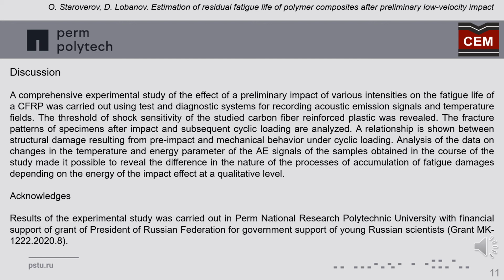The thresholds of the shock sensitivity of the studied carbon fiber reinforced plastics were detected. The fracture patterns of specimens after impacts and subsequent cyclic loads are analyzed. A relationship is shown between structural damage resulting from pre-impact and mechanical behavior under cyclic loading. Analysis of the data of changes in the temperature and energy parameters of the acoustic emission signals of the samples obtained in the course of the study made it possible to reveal the differences in the nature of the processes of accumulation of fatigue damage depending on the energy of the impact effects and the load level.